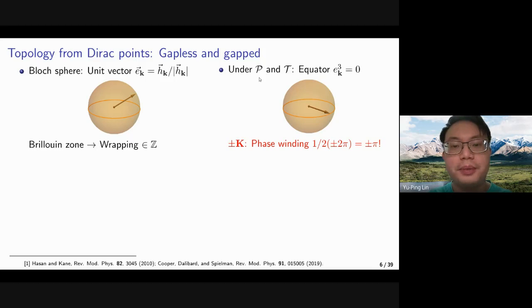If we have both inversion and time reversal, we know that it is required to have a vanishing third component. So the unit vector should always lie on the equator. It means that if we look at the plus and minus K Dirac points, if we go around them, we will have a phase winding, which is equal to spin 1/2 times plus or minus 2 pi around the equator, and it will correspond to plus or minus pi.